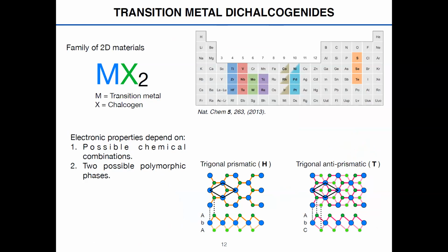First of all, depending on the possible combination of the chalcogens with these transition metals, but also depending on the two possible polymorphic phases of the transition metal. These polymorphic phases depend on how the six chalcogen atoms are coordinated with the transition metal. If the coordination is trigonal prismatic, then you have this H phase, and if the coordination is octahedral, then you have this T phase. One interesting example of a transition metal dichalcogenide of the same chemical species that has very different electronic properties between the two possible polymorphic phases is tantalum disulfide.